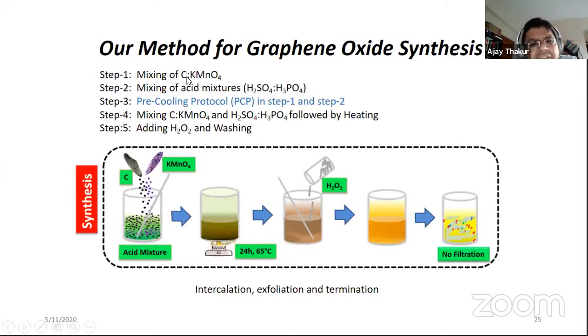So this reaction goes in the following steps. So we take graphite as the source of carbon, and that is grinded, and then we mix it with potassium permanganate, and then to this is added a mixture of H2SO4 and H3PO4, and H3PO4 is added to H2SO4 to make a milder acid. And then while this is mixed, prior to that, both the starting mixtures are cooled to about 5 degrees C, and then once these are mixed, followed by heating, and then finally the reaction is terminated by adding hydrogen peroxide.